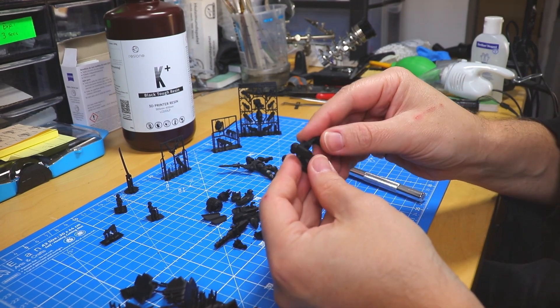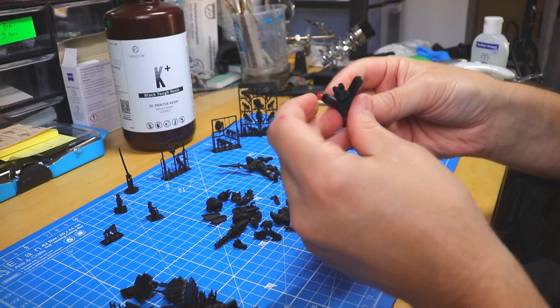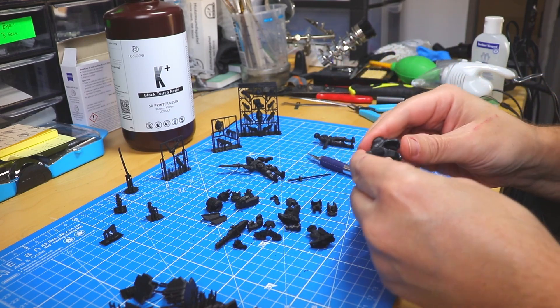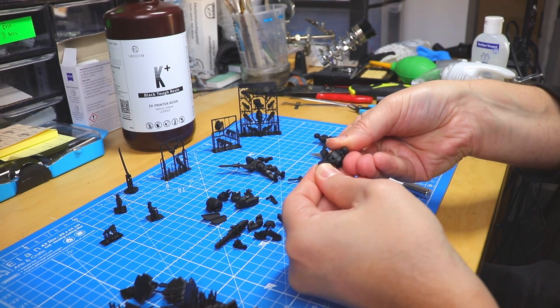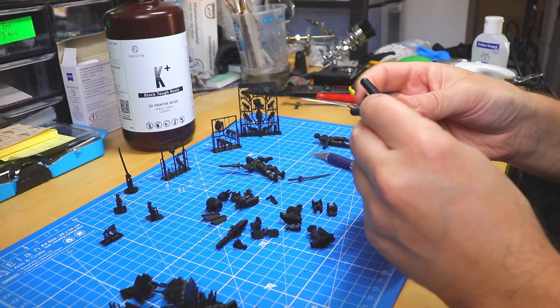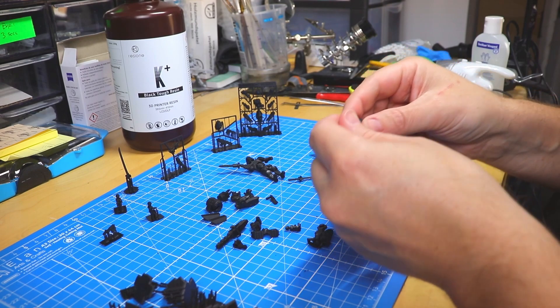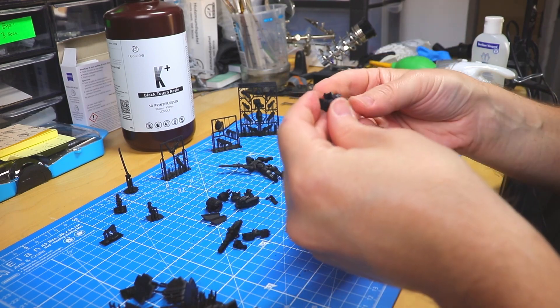Let's put them together and see how it snaps — I'm sure it will not break. A good tough resin has some flexibility to it, and that's important. Seems to come together very nicely, very good fit. The exo armor seems to work very well at the three-second exposure with this resin. It might be a good choice to print the exo armors and the accompanying pilot action figures separately with different layer exposure settings. The foot joint is very loose, so three seconds didn't work well there — maybe four seconds would be the better choice.